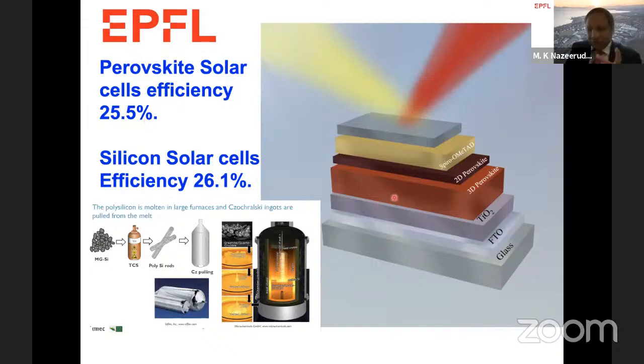If you look at the design configuration, the difference between silicon solar cells and perovskite solar cells is shown here as a contrast. On the right side, the perovskite material is sandwiched between two charge transport layers: one hole transporting material, and the other an electron transport material. All these three layers are solution processed and sintered at low temperature, 120 degrees. Compared with silicon solar cells, this is a very complicated energy-intensive process where we have to take the metallic silica and then crystallize it into monocrystalline ingots. This is a highly energy-intensive process at 1400 degrees temperature.